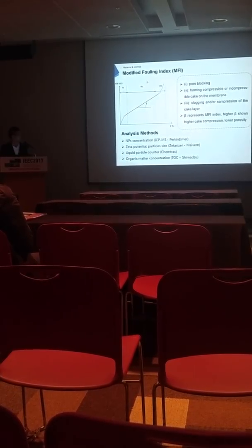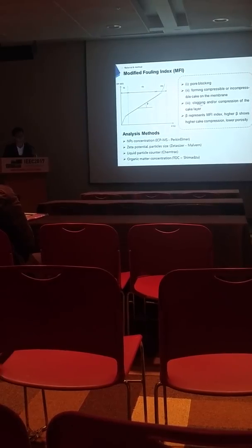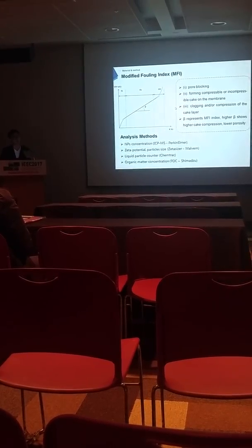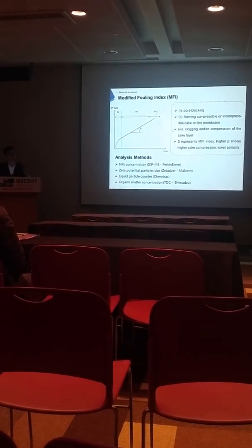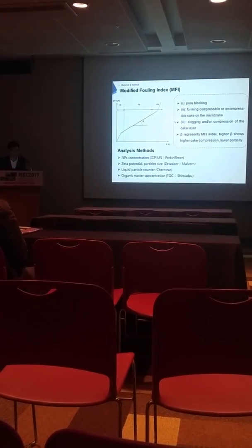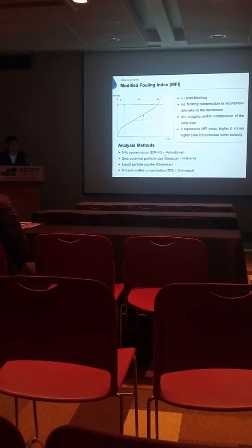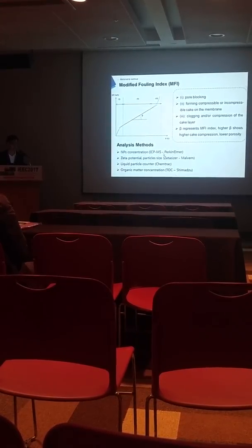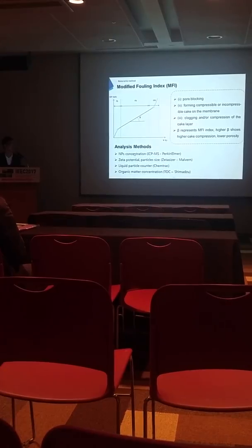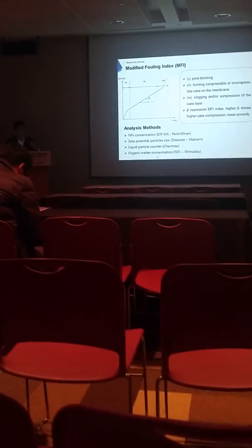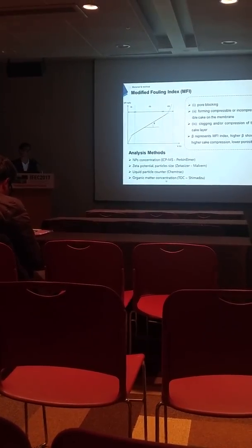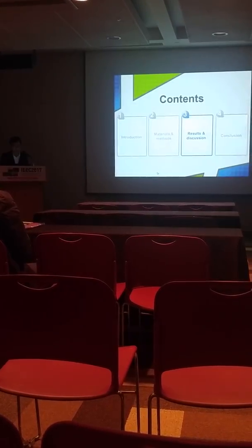And the next method that we use is the modified fouling index. Using this method, we will be able to identify what type of cake filtration the fouling created on the membrane. Besides that, we also use some other analyses such as measuring the nanoparticle concentration, zeta potential, particle size, and also the organic matter concentration in the solution.